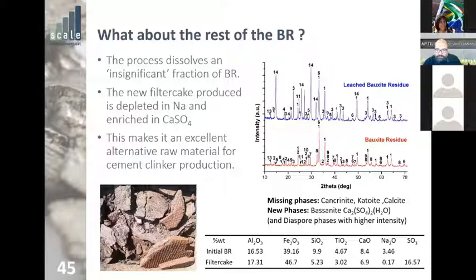In terms of XRF composition, you see it at the bottom of the screen. I have to say that this was one of the first filter cakes, so it has a high sulfur presence. The 16% is not representative. After we gained a bit more experience with the filter press, we know how to wash it better, and now it's close to 6-7%, not 16. But again, we have a filter cake that's enriched in iron, seems to be enriched in alumina because it has practically lost a lot of its weight, and it's depleted in soda. So we have taken away the major drawback of reusing bauxite residue, which is its alkalinity.